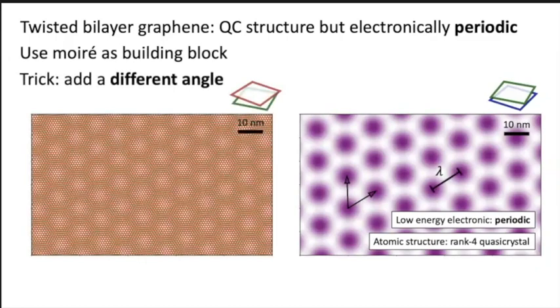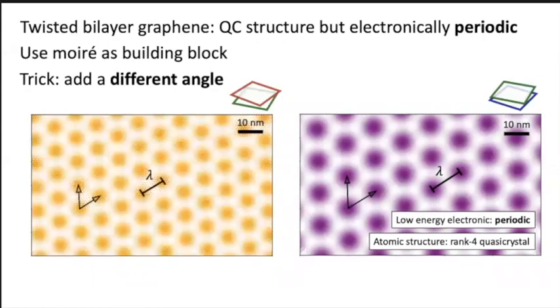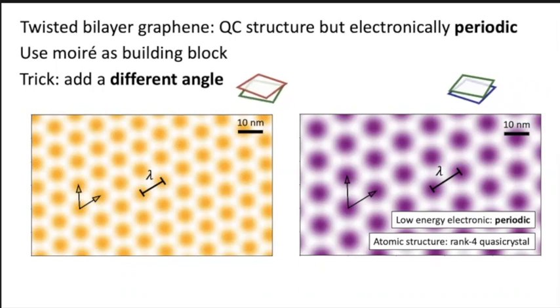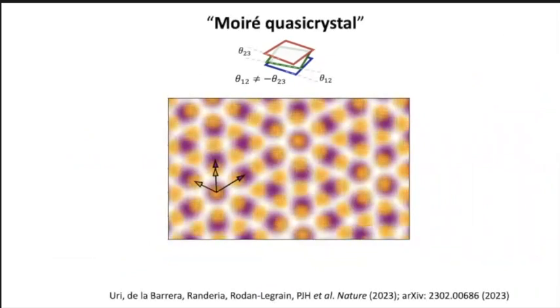We can take twisted bilayer graphene at a different twist angle. The electrons, again, here, a rank 4 quasi-crystal, but the electrons will see a periodic Moiré crystal, okay? But we can choose this twist angle and this twist angle to be slightly different, yeah? Then we can put them on top of each other. In particular, we're going to make just a three-layer structure where the middle layer is just shared, okay? And then what happens is that we will have these two Moiré patterns on top of each other.